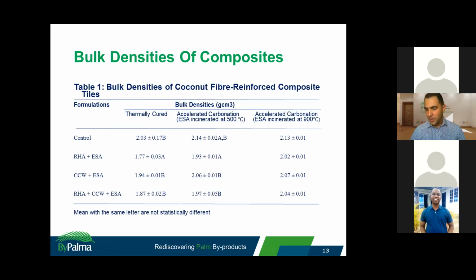Now, if you look at the flow of this table, you see thermally cured sample, accelerated carbonation, accelerated carbonation. One was done for sample incinerated at 500 degrees Celsius. One other one was done for eggshell incinerated at 900 degrees Celsius.